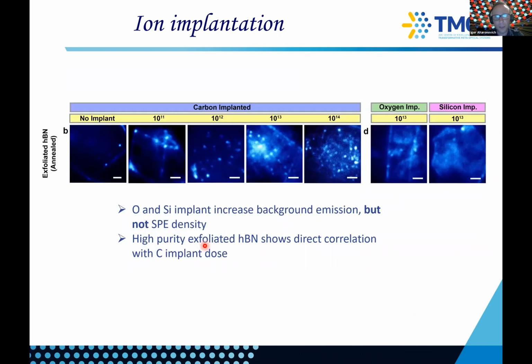And the last evidence is really to look at the dose dependence. As you implant carbon more and more, from the pristine flake to 10^11 to 10^14, you can see that the concentration of these localized bright spots, which correspond to single emitters, is basically high, and you do not see the same thing when you implant oxygen or silicon. So this is direct evidence that carbon is most likely the source of the single photon sources.